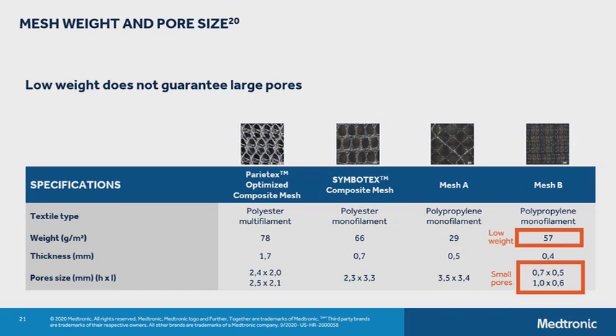What we can see here, though, for this surface density, we compare two different ventral meshes that we have out, one historical and one that is available today. We compare this to mesh A and mesh B. We can say 78 grams per meter squared, and pore size that's between 2 and 2.5. For Symbotex, it's about 66 grams per meter squared, and then the pore sizes are 2.3 by 3.3.